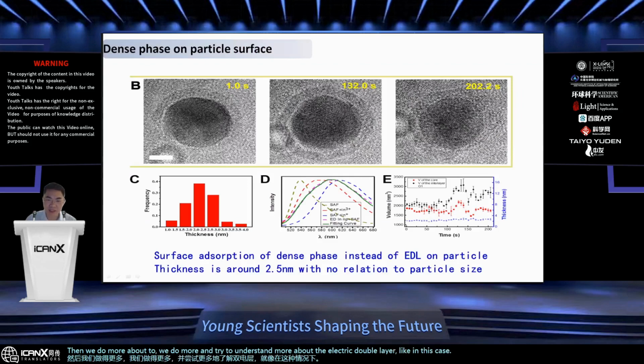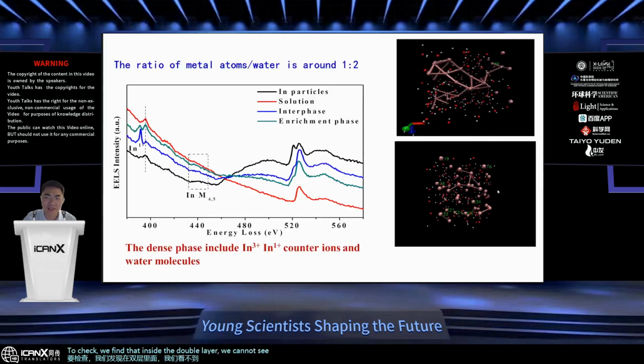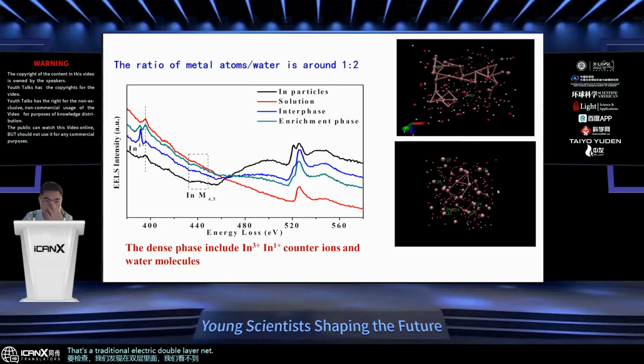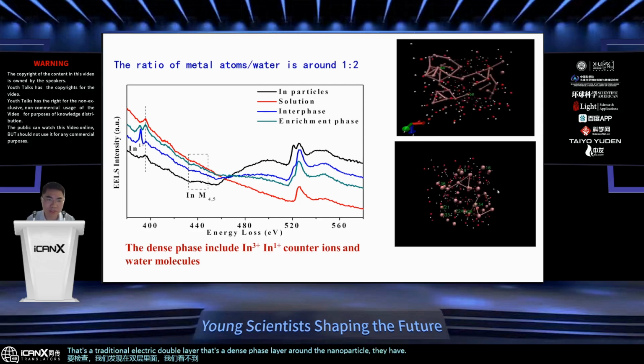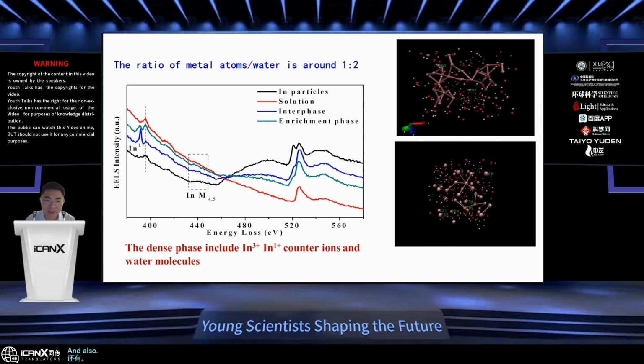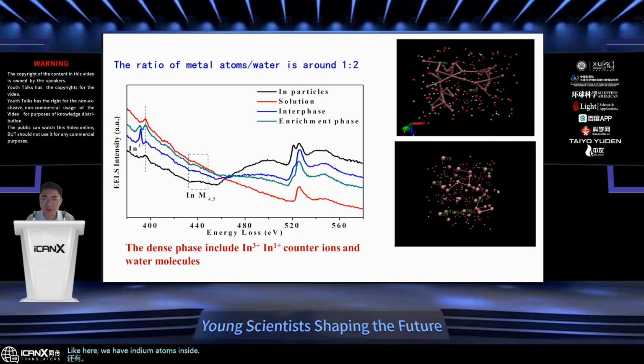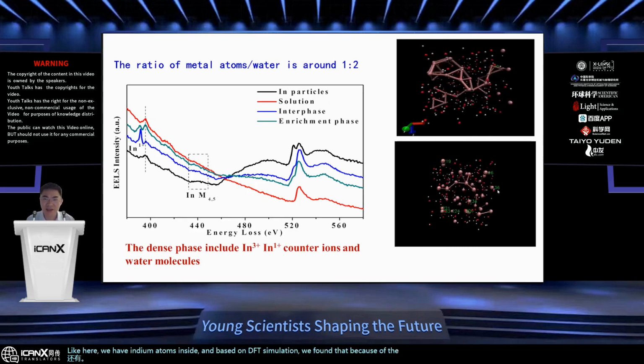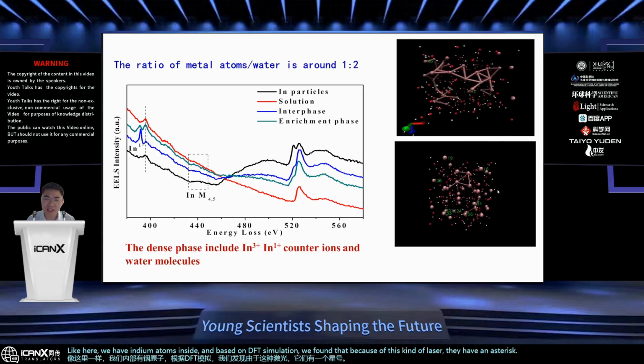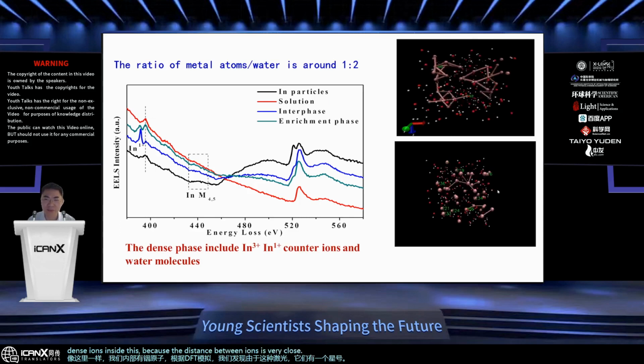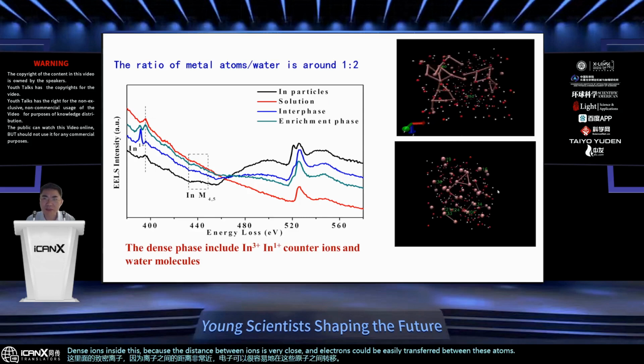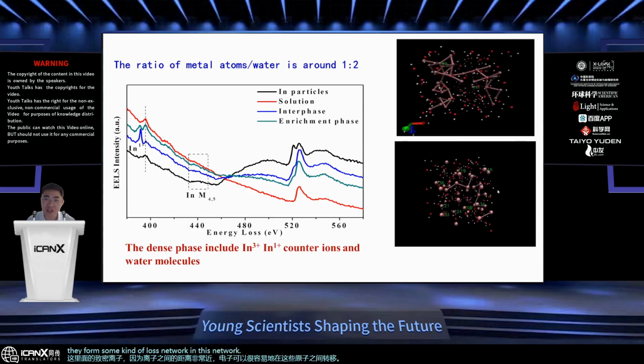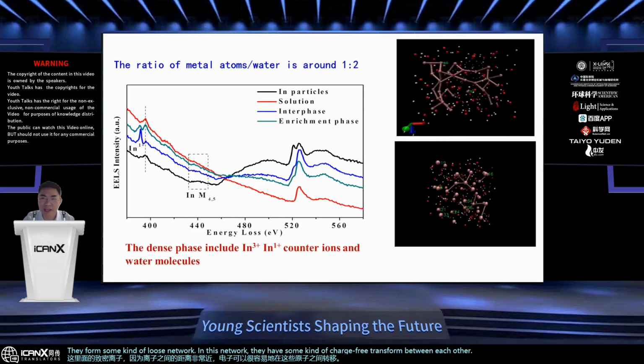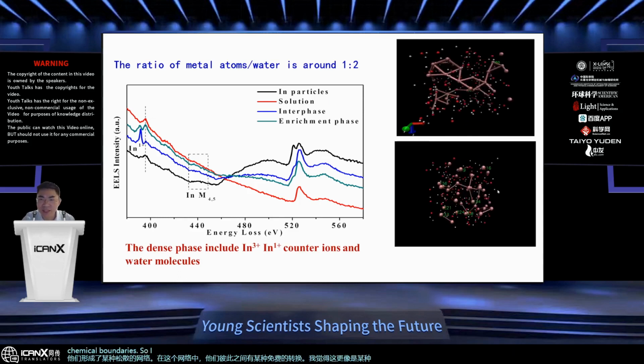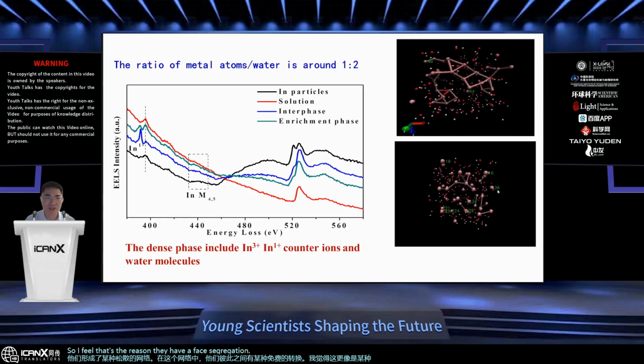In this case, we use spectra and EELS to check. We found that inside the double layer, we cannot see a traditional electrical double layer. That's a dense phase layer around the nanoparticle. They have ions and molecules, like the water molecules and the counter ions, and here we also have indium atoms inside. Based on DFT simulation, we found that because of this kind of layer, they have ultra dense ions inside, because the distance between ions is very close, and the electrons could be easily transferred between these atoms, and then they form some kind of loose network. In this network, they have some kind of charge transfer between each other. I feel that's more like some kind of chemical bond. So I feel that's the reason they have a phase segregation between the bulk liquid and the solid part.